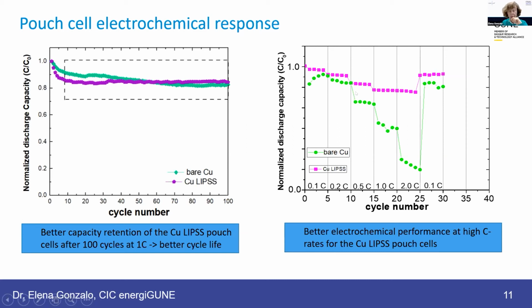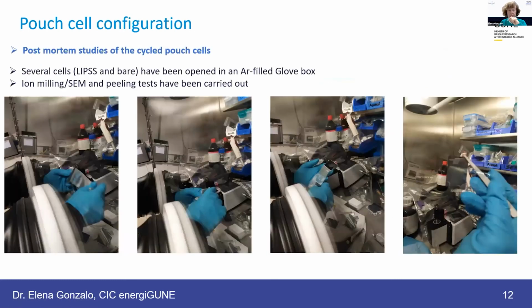In the case of the right-hand side graph, where we did the C-rate capability, what I mean is we were increasing the current density from 0.1C, that means 10 hours to charge the material and 10 hours to discharge the material, to a faster test, applying current to charge and discharge for 30 minutes. You can see clearly the difference between the cells that were cast on copper LIPSS, these pink ones, and the ones with bare copper foil. There was a huge decrease in capacity when we were going to very high current density. So we got better electrochemical performance at high C rates for the copper LIPSS.